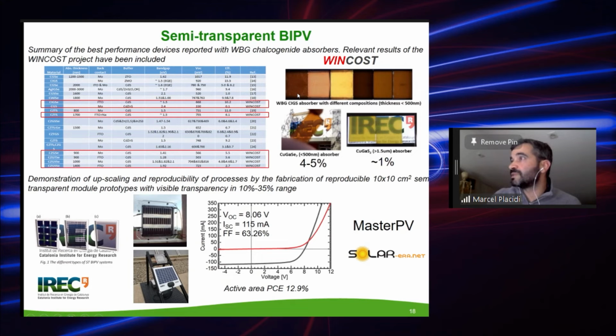several wide bandgap CIGS absorbers with different compositions. Here we were varying the anionic compositions. Here we can see the absorber. So here the copper gallium selenide absorber, and the copper gallium sulfide absorber. For this absorber, we demonstrated an efficiency close to 5%. In fact, it was 4.4, 4.5, I don't remember right now. And for the copper gallium sulfide, we demonstrated an efficiency close to 1%, a bit less. So that's interesting because, as we can see there, this absorber shows a certain degree of transparency.